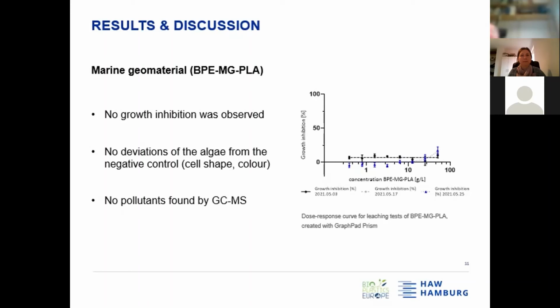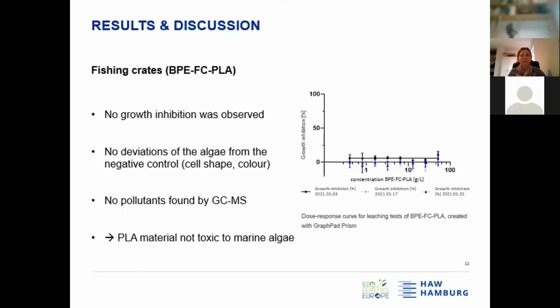And during the 3 replicates, so in all 3 tests, no growth inhibition of the algae was observed, and also no deviation of the algae from the negative control in cell shape and color was observed. And we also didn't find any pollutants by GCMS analysis. So here are the results for the PLA material for the fishing crates, and like for the Marinegeo material, we didn't observe growth inhibition and also no deviations in cell shape and color from the negative control was observed. In addition, we found no pollutants by GCMS analysis.